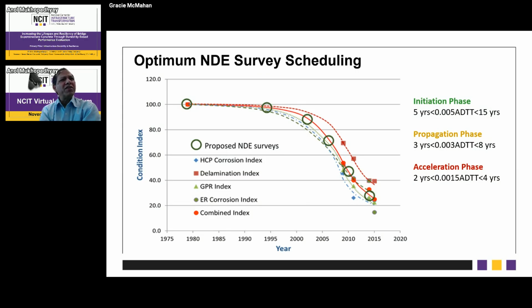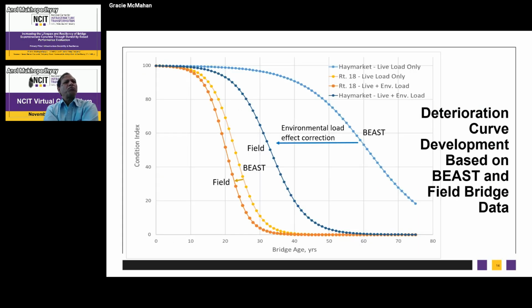The one important thing is, if you go to a bridge and it is in an acceleration phase, your frequency of going to the field should be more than 2 years, less than 4 years. So if you go to the field and do a real NDT evaluation and damage curve over time, a meaningful curve can be generated in a minimum of 2 to 3 years' time. And our project is 2 years, so it is time-bound, and it is actually really difficult to get a complete picture of the deterioration curve within this small 2-year project. Go to the next, please.